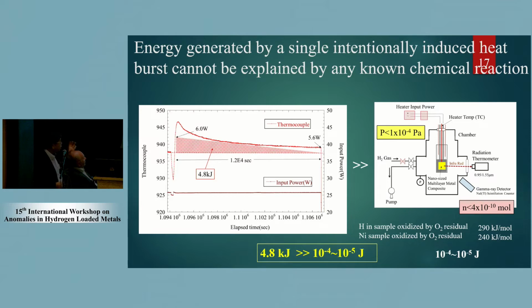But the excess heat experiments are under vacuum conditions, and we have some residual gas in the chamber, but the amount of residual gas is very low. If we postulate that hydrogen and the sample are oxidized by the residual O2, it is about 10 to the minus fourth to 10 to the minus fifth. So it is not so large, and it cannot be explained by any chemical reactions, even for a single perturbation.